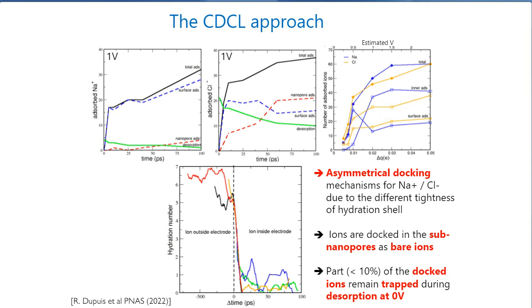You can see that orange is always the anion — the chlorine ions — blue is sodium, and black is total. The docking is not symmetric in time. The chlorine ion, being a bigger ion, has a less tight hydration shell compared to sodium, which is a smaller ion with water molecules closer to it and more energy in the hydration shell. So the chlorine ions lose their water shell more easily than sodium ions. They find their way into the pores faster, but they are bigger, so they don't diffuse as deeply. The sodium ions accumulate on the outside surface first and require more voltage to loosen their hydration shell before they can get into the pores. Finally, doing the cycling — polarizing and un-polarizing the electrode back to zero — we actually lost about 10% of ions that remain trapped inside the electrodes.